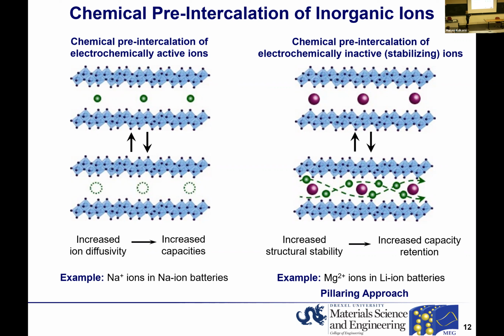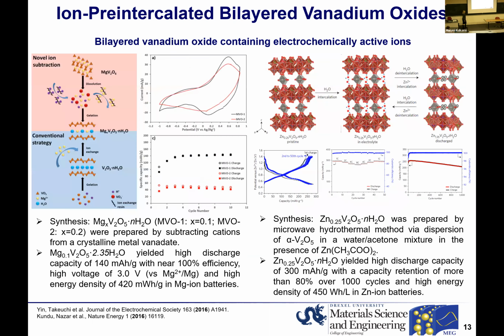On the other hand, we can chemically pre-intercalate electrochemically inactive ions, for example, magnesium ions in the case of lithium-ion batteries. In this case, chemically pre-intercalated ions essentially serve as pillars that stabilize the layered structure further through the ionic bonding between the ion and the vanadium oxygen layers. So in this case, we expect to see much improved electrochemical stability during cycling.